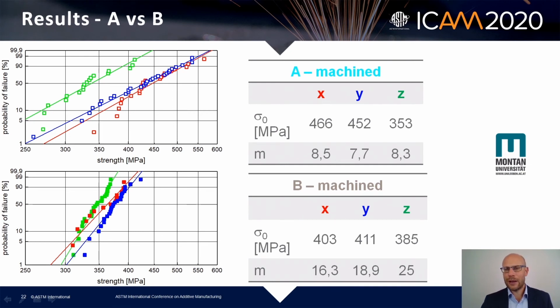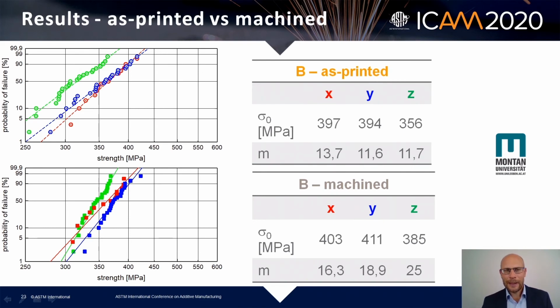And if we compare now machined and as printed, again, so you already know the machined values from B, and if we measure them as printed, you can see that there is, at least from the Weibull statistics, a significant difference in the as printed value. But the difference is still not too big, but it's here. And Weibull modulus is getting a little bit lower. Also, the values are still comparable. They are still within the distributed strength, and there is not such a big impact from the machining. But you can see that at least in Z there is a difference.